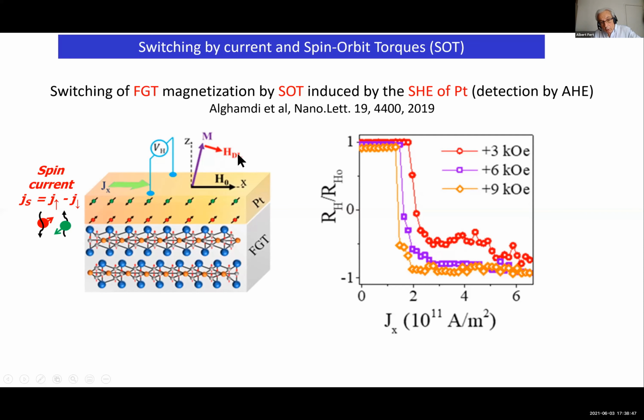So the damping-like torque acts like a field, but the reversal is only possible if at the same time one applies a small field along the direction of the current, this H0. And in this experiment, for example, you can see the amplitude of this field used to generate this experimental curve, 3, 6, or 9 kilo-oersted, which is relatively small. But it's not different from what is observed generally. Not always, because I am working a lot now on 3D materials on field-free switching of magnetic layers.